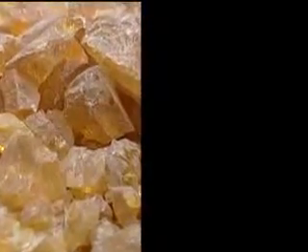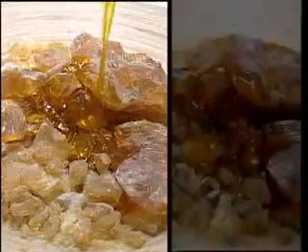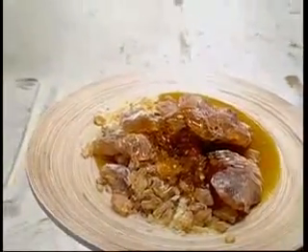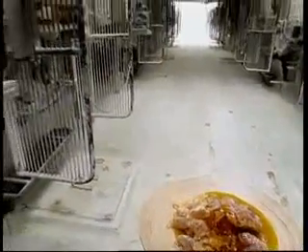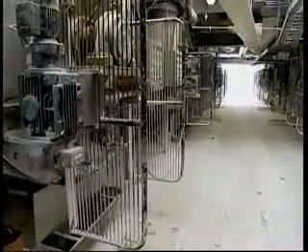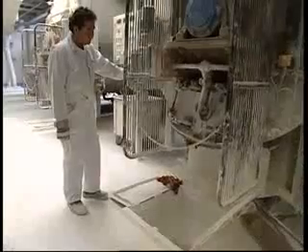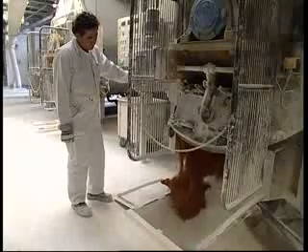The linseed oil is mixed with natural rosin, harvested from certified wood plantations. The linseed oil and rosin is mixed and heated in large vats. As a result of the heating and oxidization of the linseed oil and rosin, a mixture is created which forms the basis for producing linoleum. After 24 hours, the rosin and linseed oil oxidize to a homogeneous mass. We call this mixture linoleum cement.